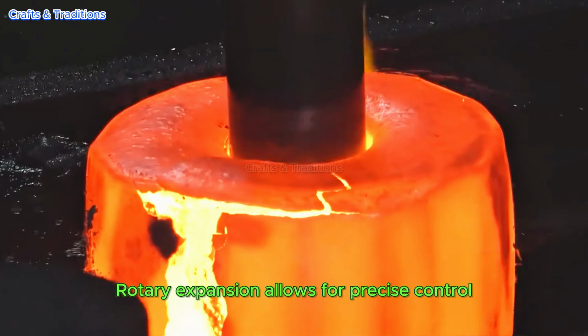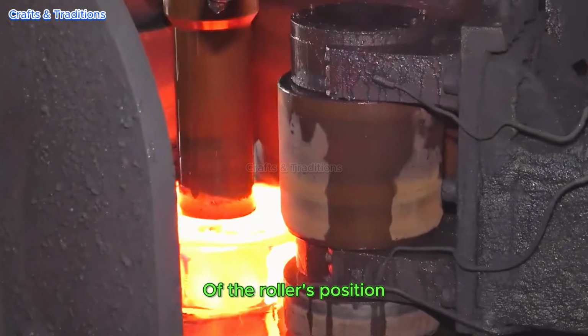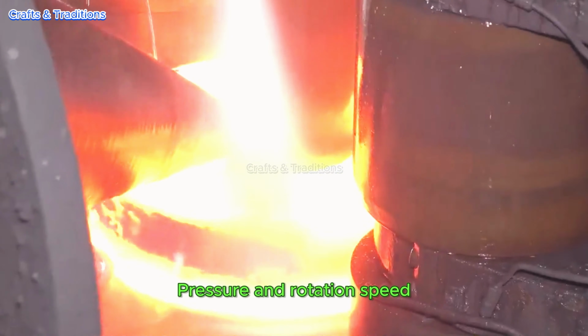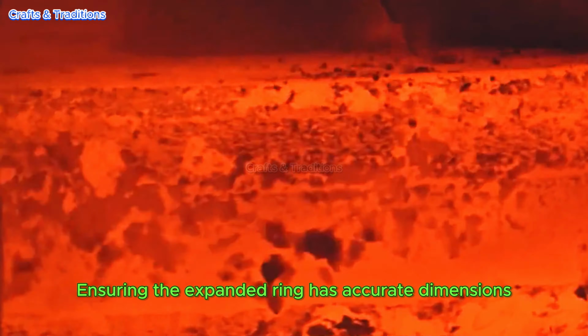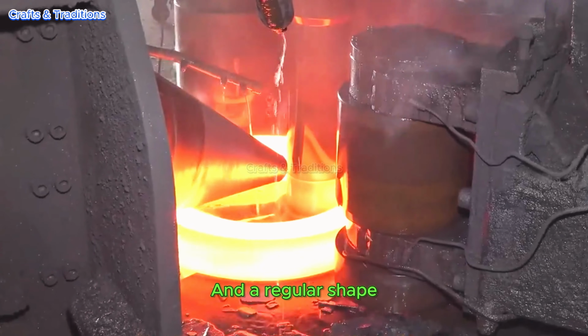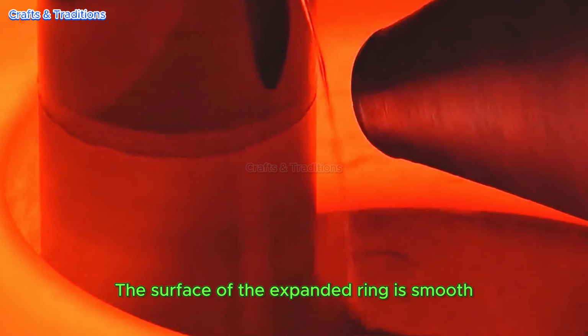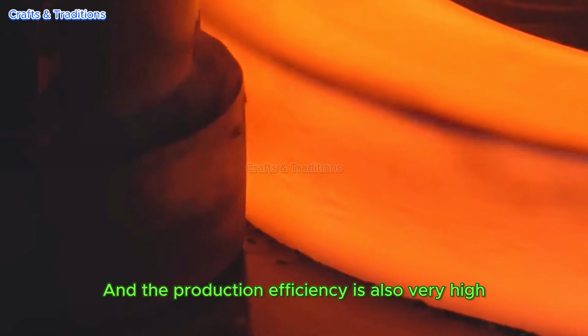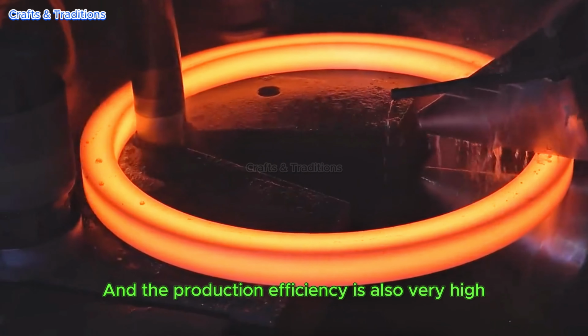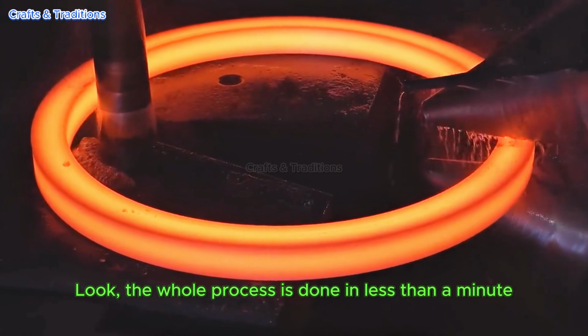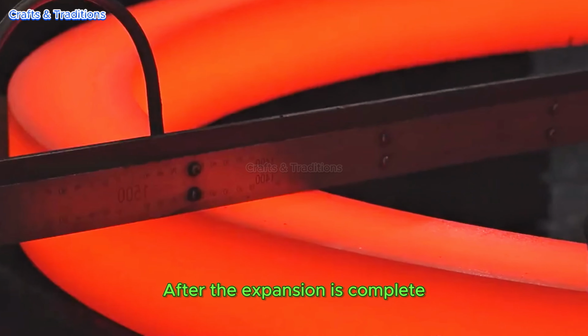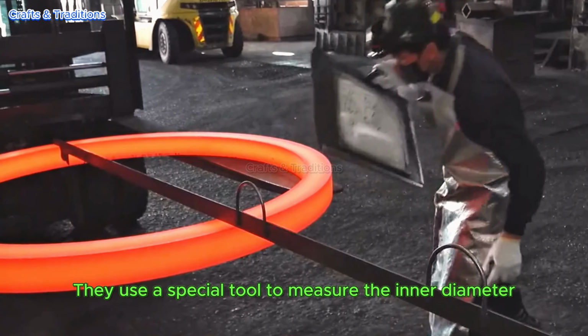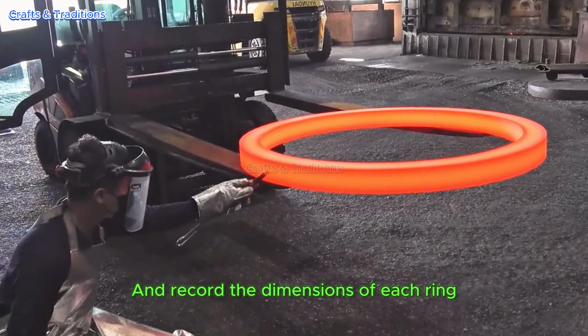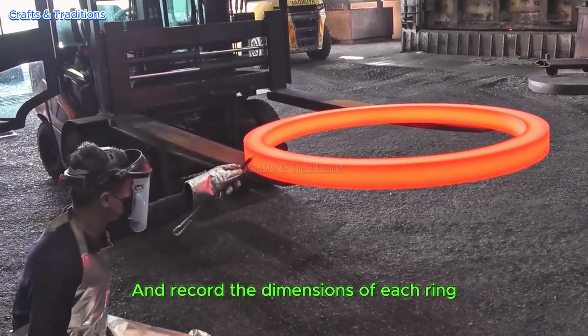Rotary expansion allows for precise control of the roller's position, pressure and rotation speed, ensuring the expanded ring has accurate dimensions and a regular shape. The surface of the expanded ring is smooth, and the production efficiency is also very high. Look, the whole process is done in less than a minute. After the expansion is complete, they use a special tool to measure the inner diameter and record the dimensions of each ring.